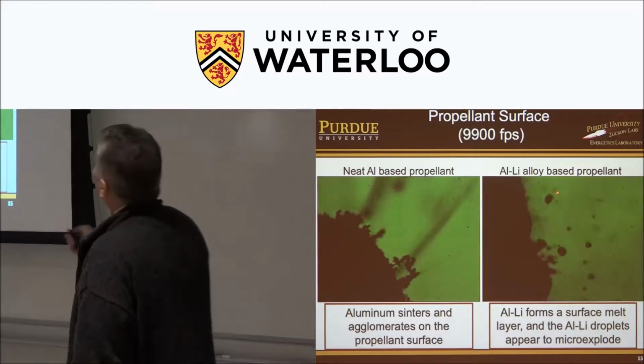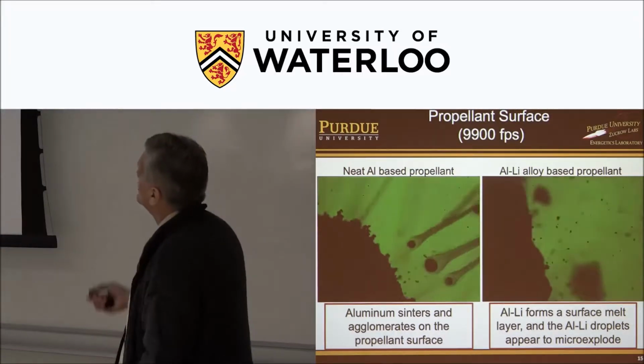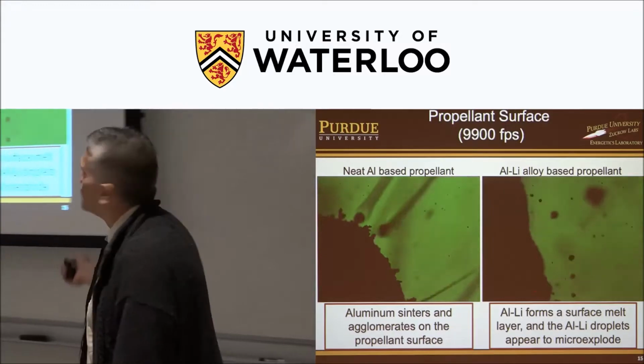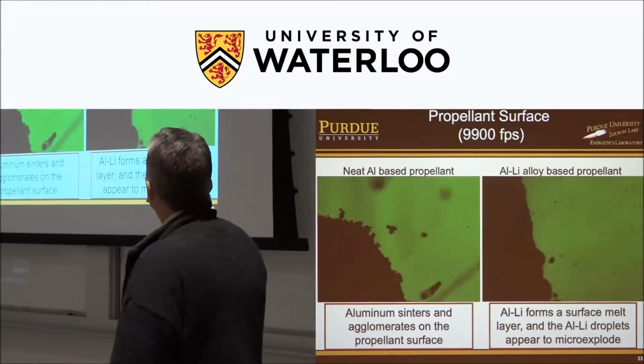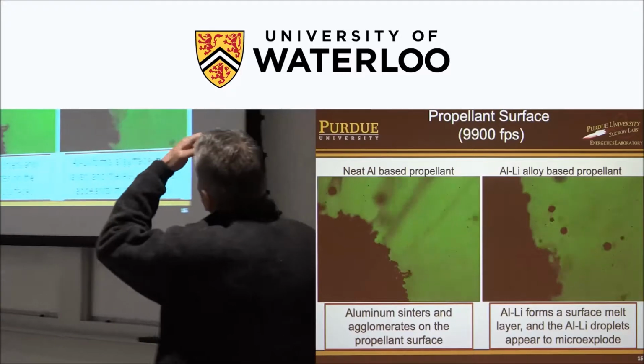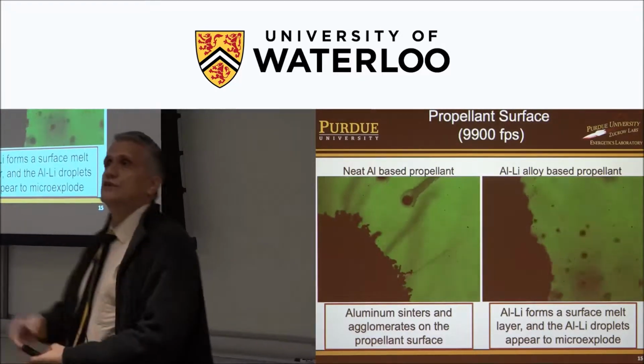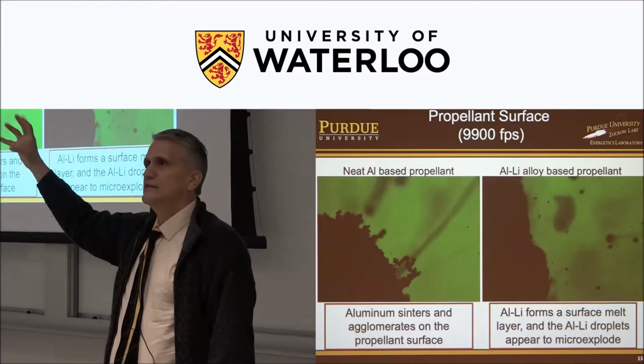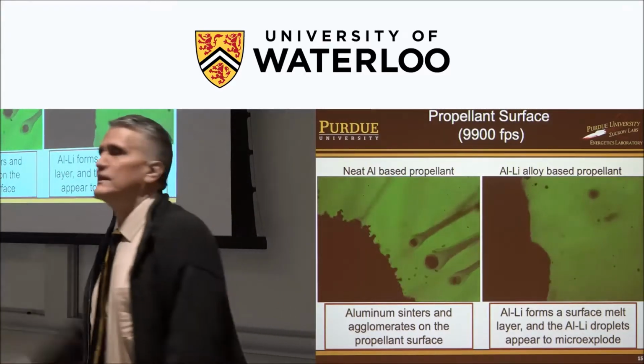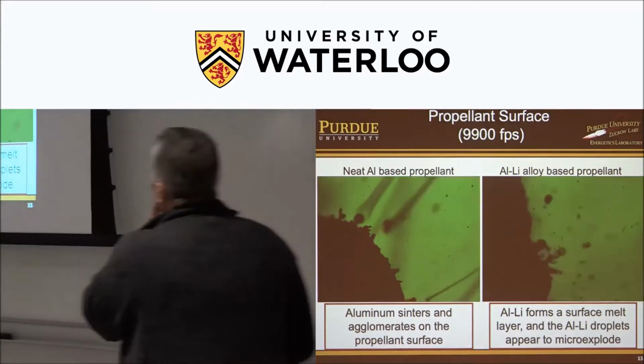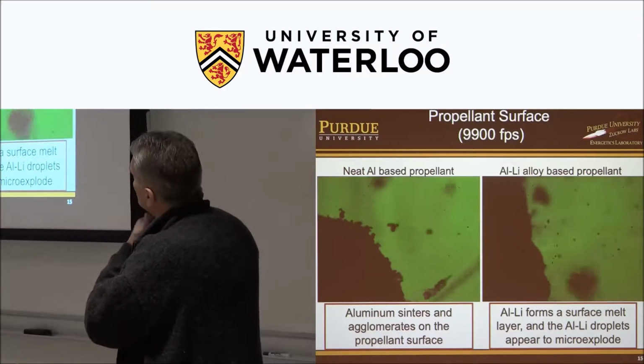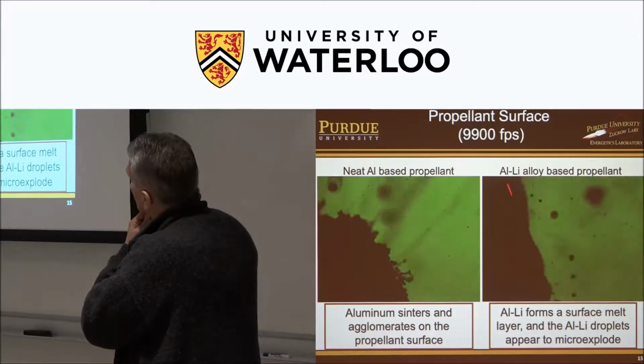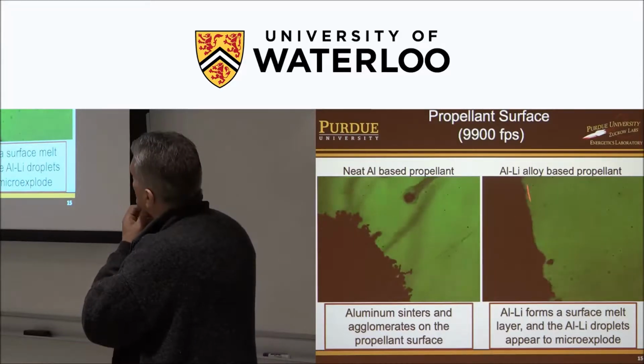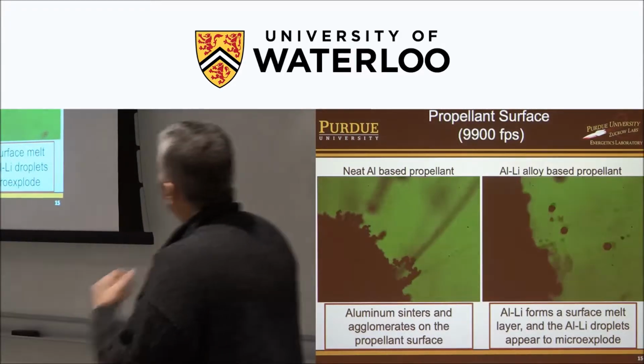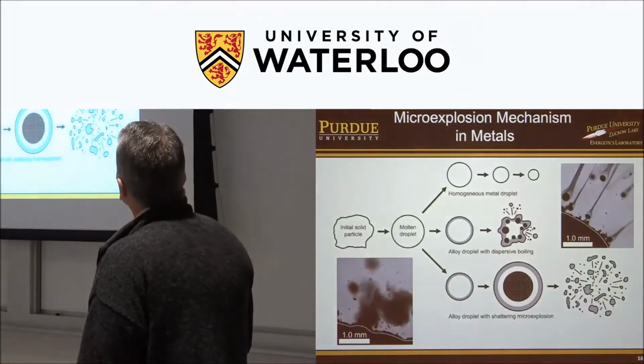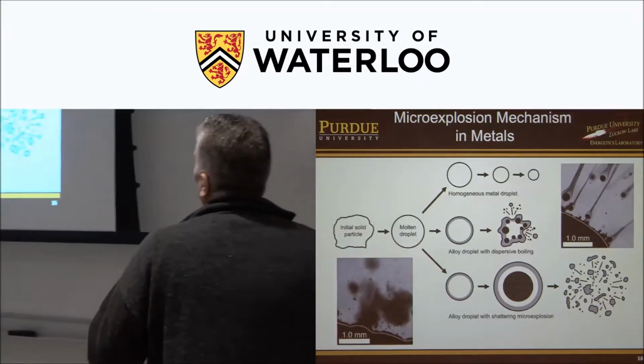This is typical. If we replace the aluminum with aluminum lithium alloy, the whole surface changes its characteristics. It's kind of bubbling on the surface. It'll throw off droplets, and then you can clearly see these micro explosions. The droplets just self-disintegrate. So what's going on there? Also, in recent work we're going to begin looking at is to understand if there are reactions with that lithium at or near the surface. I really think there are based on some data. So this is how we've explained what's going on.